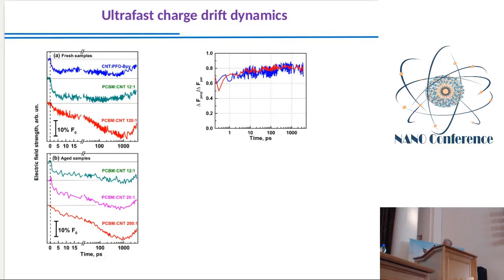So here is the electric field. We see a very fast drop of the electric field during less than 1 picosecond, limited by our time resolution, and this drop is caused by generated excitons. When we generate an exciton, we have an electron and hole together. But when we apply an electric field, this electric field separates electron and hole, and this separation increases the dielectric constant of the material, and when the dielectric constant increases, the electric field drops down.